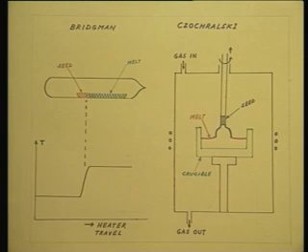Alternately, you could also move the quartz ampule in this direction. Same purpose will be served. Instead of moving the heater, you could just move the quartz ampule in this direction. Even in that case, the seed end of the melt will come into the low temperature zone and therefore, it will get solidified in contact with the seed crystal. It will get solidified as a single crystal and will realize a single crystal.